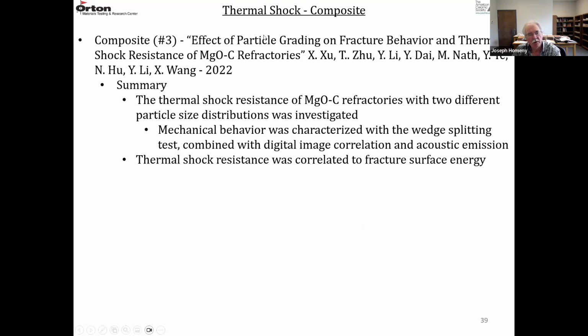This other paper I picked shows the effect of particle grading on the fracture behavior and thermal shock resistance of these MgO carbon composites. This is a 2022 investigation. So they looked at the thermal shock resistance of an MgO carbon refractory with 2 different particle size distributions, basically a fine distribution and a coarse distribution. And they used the wedge splitting test to measure the mechanical behavior.